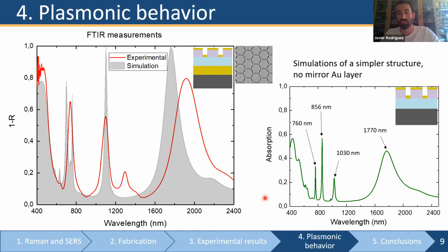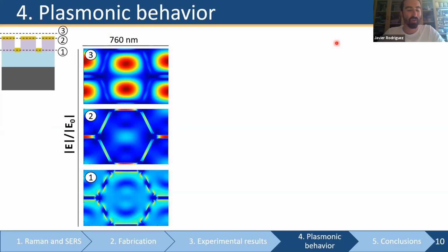So if we take a look at the absorption of this structure without the mirror, we can quickly identify 4 absorption peaks, which could be related to these 4 absorption peaks that you can see here in the simulations. So in principle, the excitations of the lattice were at least very, very similar. So if we take a look at the excitation of the near field in these structures, we get something like this. Before going into detail of these maps, you should know that what you're seeing here is a distribution of electric field. The redder the color, the higher the electric field intensity.